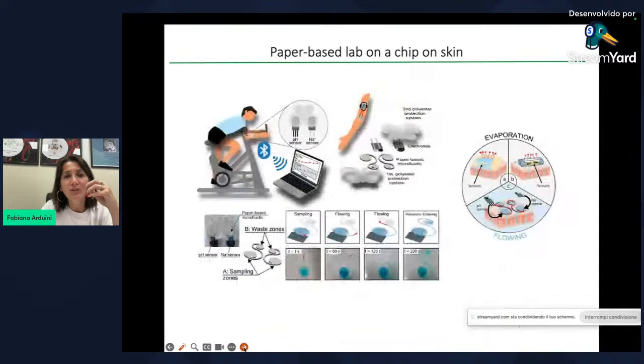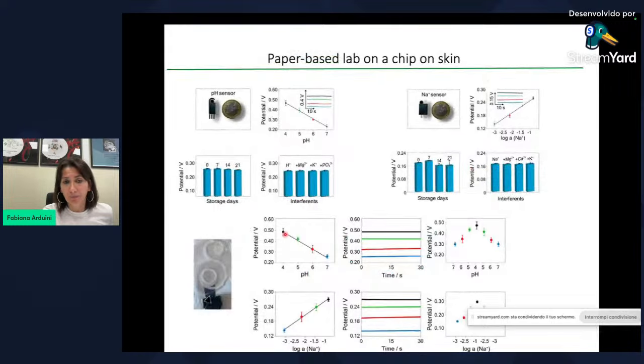And recently we demonstrated that it's possible also to detect different targets in continuous. In the case of pH measurement and sodium measurement, this is very important, for example, for detection. In this case, we have the sampling pad, and we have the pad that works like a reservoir and a wicking pump, and we demonstrate this by measuring pH and sodium.